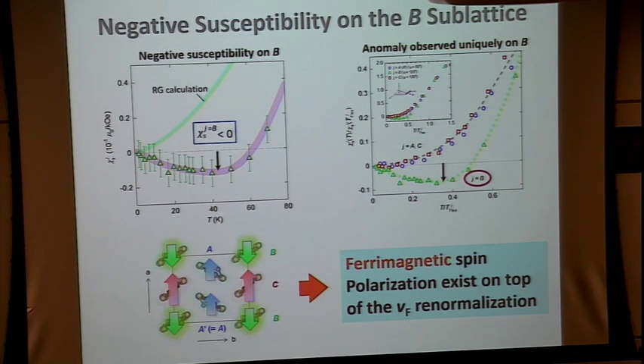Please take a look at the data here. This is the experimental data for the B site. And this is the RG calculation, a large difference. The RG calculation cannot explain the behavior. And this is the comparison of the experimental data for A, B, and C sites. A and C sites show a very normal behavior, but only the B site has negative values. It's a negative spin susceptibility. It is very, very curious because this is a paramagnetic state, no magnetically ordered state.